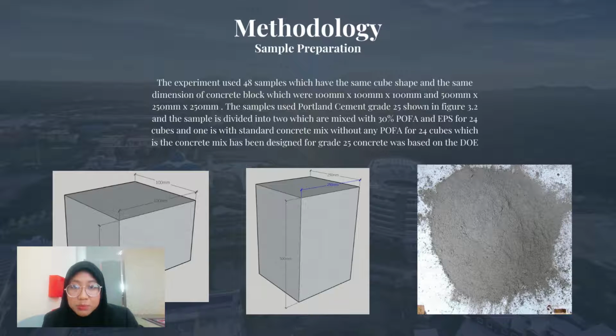Okay, for the sample preparation, in this experiment, we'll use 48 samples which have the same cube shape and the same dimension for each concrete block. First, for the compression test, we'll use the cube test. The cube test is 100 mm cube. And for the pull-out test, we'll use the rectangular size, which is 500 mm times 250 mm times 250 mm.